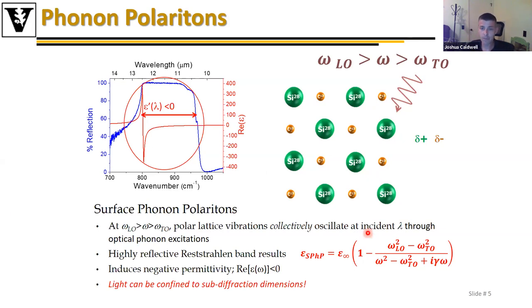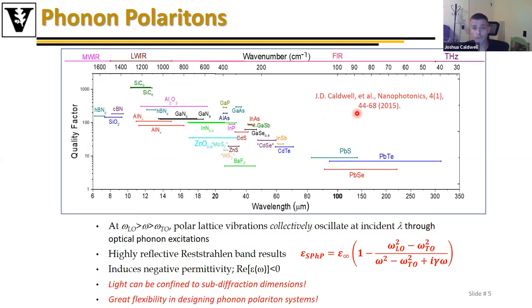Now, this is defined by this dispersion relationship here rather than a Drude form, where this is still a Lorentz oscillator, but now it has bounds between the LO and TO phonons, right? And so this means that we have a bandwidth over which we can operate that's material dependent, but it also means that the dispersion of the polaritonic mode, or the dispersion in the permittivity, is quite rapid within this range, and thus the group velocity, which is the derivative of that dispersion, is quite slow. So for opportunities where you want slow light, phonon polaritons provide a very low loss and very slow light medium to operate with. And of course, you can choose a whole broad range of these different materials, which gives you a broad range of frequencies over which you can operate.